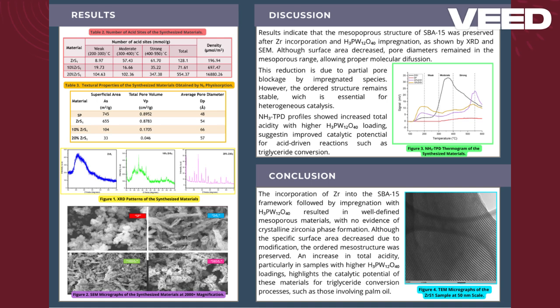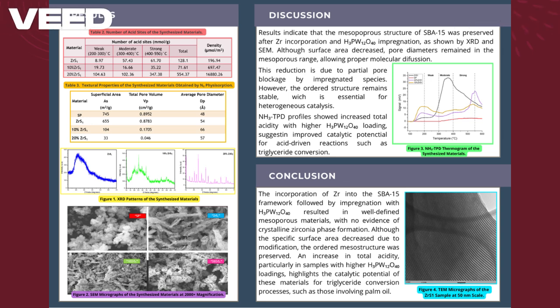Textural properties evaluated by nitrogen physisorption, Table 3, indicate high surface areas for SP and Zr-1, consistent with their preparation method. Impregnation with heteropolyacid reduces surface area, 104 and 33 square meters per gram for 10% Zr-1 and 20% Zr-1 respectively, and total pore volume, 0.1705 and 0.046 cubic centimeters per gram, but increases pore diameters, 66 and 57 angstroms, which may favor accessibility during catalytic reactions.